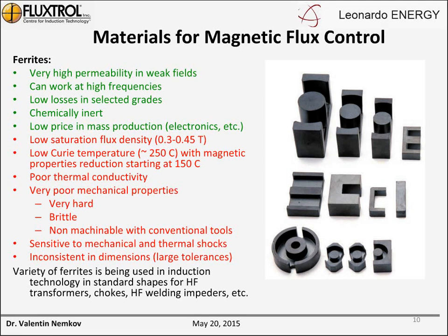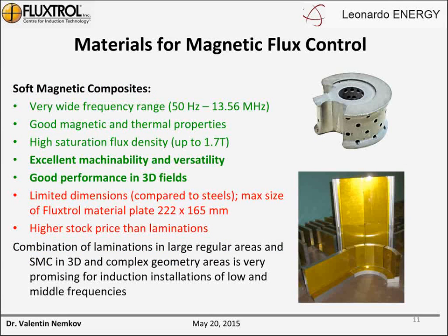A variety of ferrites is used in induction technology in standard shapes for high-frequency transformers, chokes, high-frequency welding, impeders, etc. Finally, soft magnetic composites. They can work in a very wide frequency range, from line frequency to 13.56 megahertz, covering actually all the range of frequencies used for induction heating. Good magnetic and thermal properties, a high saturation flux density. For low frequency material, it approaches 1.7 Tesla, similar to laminations.